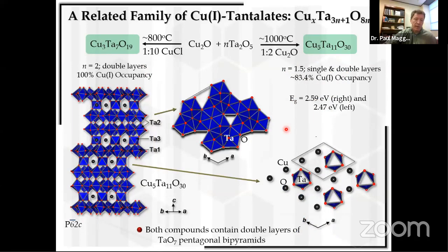So you can make these all the way up to 100% copper within the material, with, again, pentagonal bipyramidal layers that are either single pyramidal layers or double pyramidal layers. In this case, this composition leads to n equal to 2, strictly double layers. This composition of 5, 11, 30, still copper 1+, leads to an n of 1.5, which is a mixture of single and double layers of these pentagonal bipyramids. And again, these are all visible light.